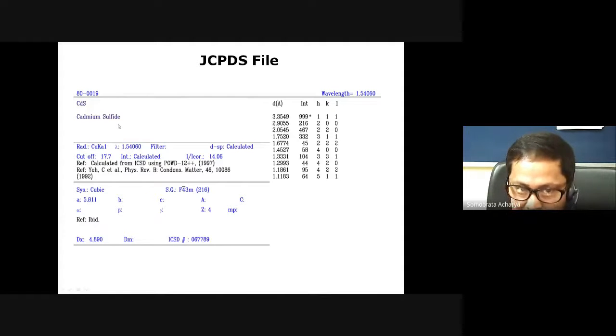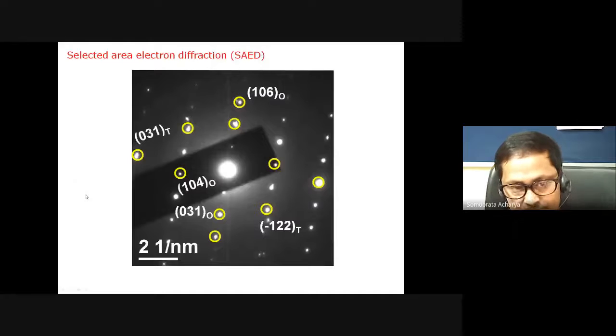For example, what is written here? It is written cadmium sulfide. So this is a standard JCPDS file for cadmium sulfide, and a number is given, 80-0019. So if you match this D spacing with certain planes, then eventually you can say that my material is cadmium sulfide. The D spacing that is measured is assigned to some HKL, which is say 111 here. And once you do that, eventually you can define the crystallographic phase to be cubic. So this is a cubic cadmium sulfide, and that is being measured from the high resolution